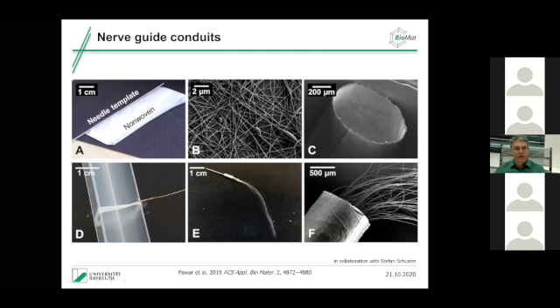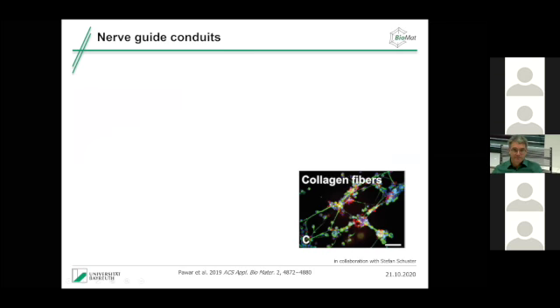Second setup that we used, I've shown you before the self-rolling films. We can also use silk nonwovens per se and roll that up and then bring in the collagen fibers. So this setup is more similar to the setup of the Hannover group, but instead of having a cover vein, we now have a silk nonwoven, and we have collagen fibers instead of the silk fibers. And this setup also works quite well.